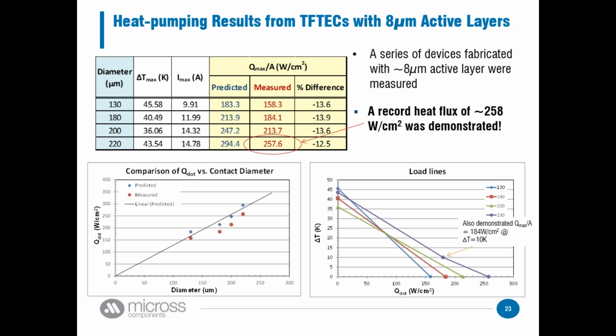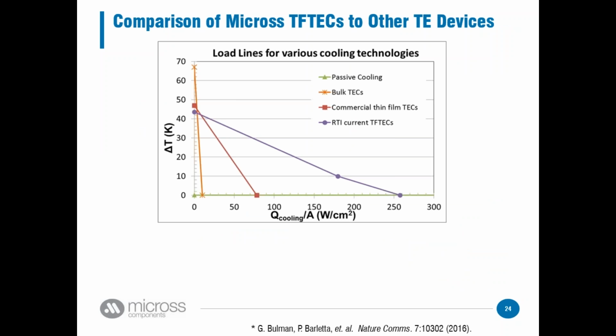We were also able to demonstrate 180 watts per centimeter squared at a delta T of 10. And again, let me remind you, that means the object we were cooling was actually 10 degrees cooler than the heat sink. So even though we were working against a 10-degree temperature differential, we're actually able to move 180 watts per centimeter squared. So how does that compare to other devices?